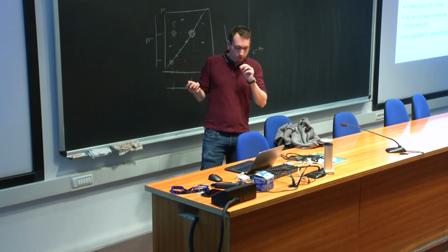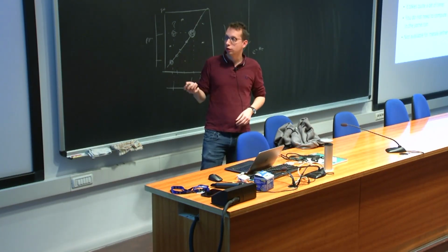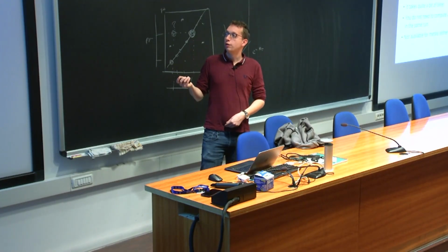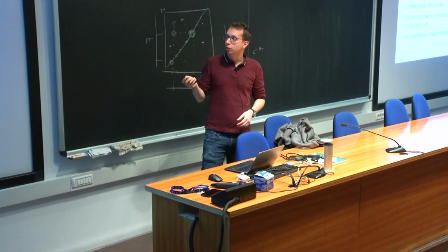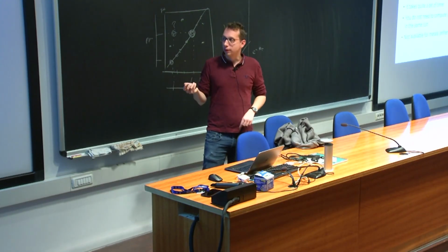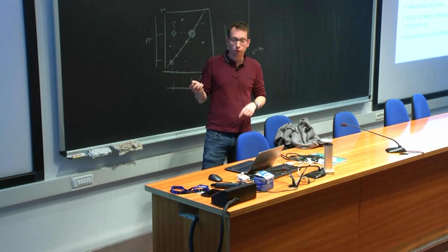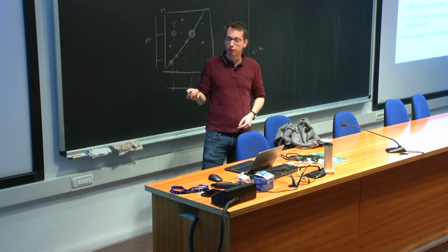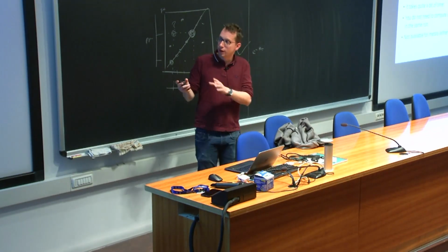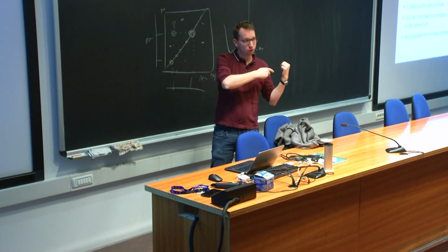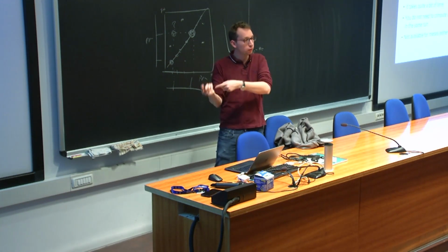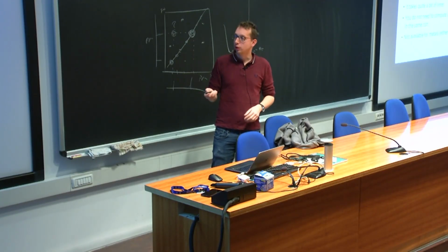However, there is a small quirk in how Phonon works. If you are doing a Phonon dispersion calculation, like if you're computing a regular grid, epsilon will always be set to true. And I found no way to set it to false. It will always compute epsilon. So if you are really on the limit of your computing time, you may want to do Q equals 0 by itself first, setting epsilon to false, and then do the rest of the grid. So it will not compute it.